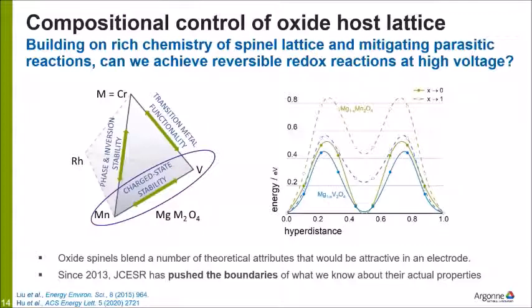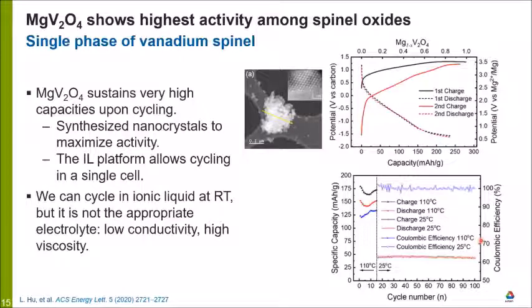So here we can see, for instance, the manganese, which you've already seen this data presented earlier, and now these blue calculations are for the pure vanadium analog. And you can see the vanadium certainly seems to lower the energy barrier quite dramatically. And it should also stabilize, the manganese, however, should stabilize the charge state. So by combining these two materials, the hypothesis is that we can perfect the cathode development. So indeed, we were able to synthesize nanoparticles of the magnesium vanadium oxide Spinel and get single phase